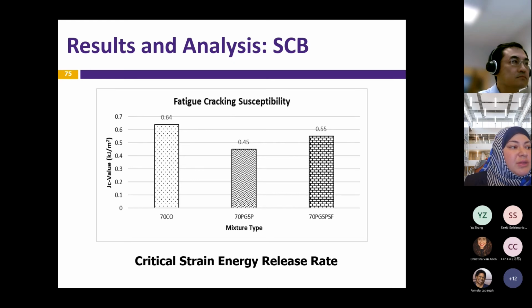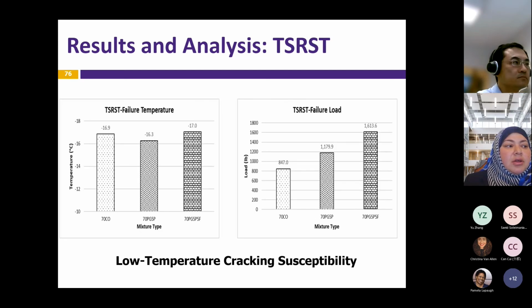We also did SCB testing. And as you can see here, adding the sodium alginate fiber improved the mix cracking resistance because it's higher than with the RAP content. We also looked at the low temperature cracking resistance by running TSRST. And as you can see, the temperature decreased and the failure load increased, which means that it's improving the susceptibility to low temperature cracking.